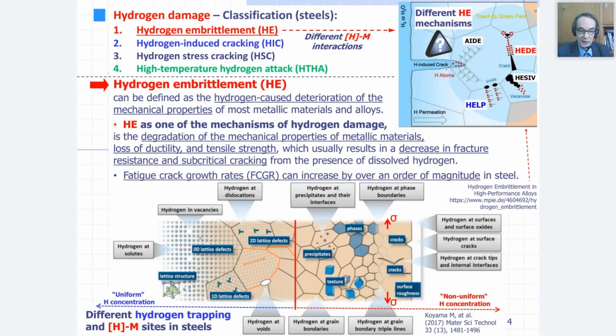Generally speaking, statistically, we can say that under no stress and after some time, we have a relatively uniform hydrogen concentration, which is not critical for hydrogen embrittlement. On the right side, you can see that we have a stress marked with sigma. Due to the stress, we have a high hydrogen concentration in the tensile area of the material, where hydrogen is